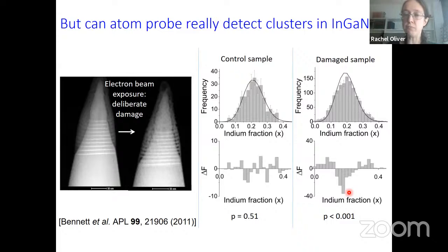There is clustering, there are regions of high indium content. The probability of this distribution occurring randomly is about a half, so quite likely. The probability of this distribution occurring if we've got a random alloy in our indium gallium nitride is less than 0.001. So this is very, very unlikely to be a random sample. It really does have indium clusters, but they've been created by the electron beam.